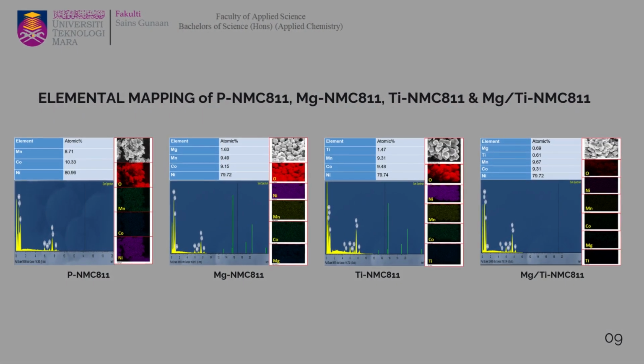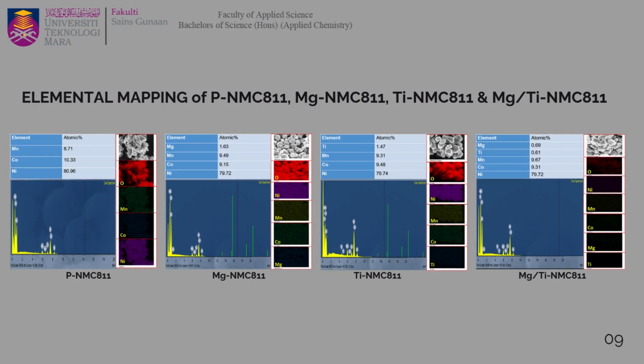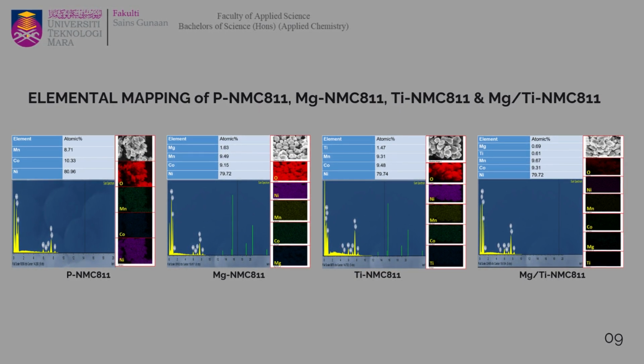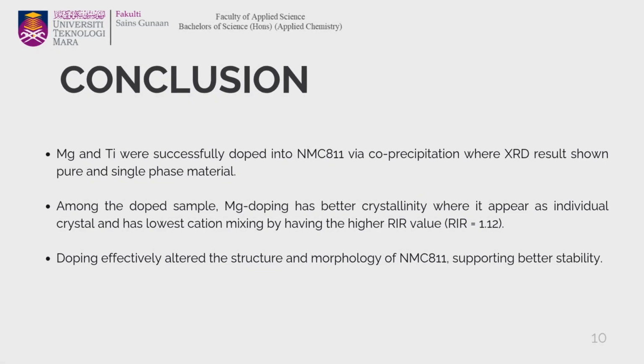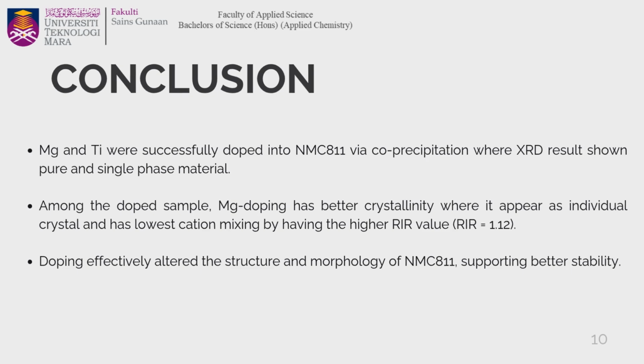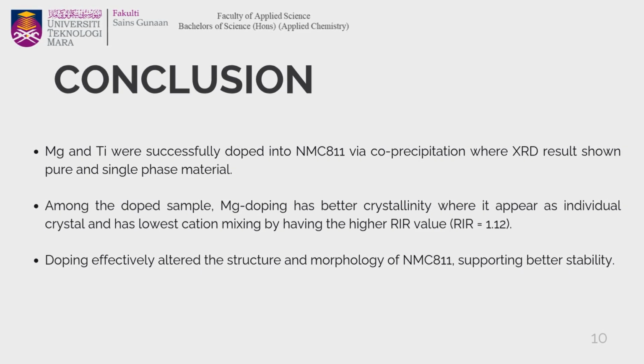And last but not least, the last characterization is the elemental mapping. So this slide shows the elemental distribution, whereby we can see from the mapping result and the EDX result, as we can see, for all the samples the elements are evenly distributed. According to the distribution of color, it is well distributed. And in the table presented here, we can see the elemental distribution, which proves the existence of these dopants in NMC 811.